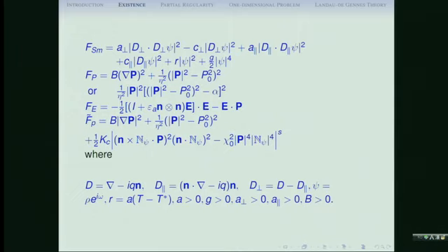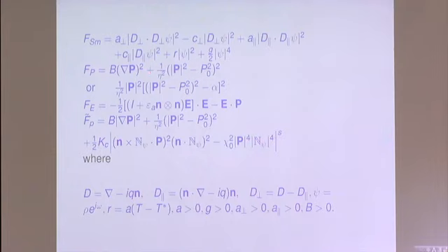When you consider antiferroelectric cases, you can put up to sixth order terms, and then if you want to, you can also put divergence P minus C0 squared, such terms. Oh, yeah. So there are many different terms. You can also have terms like divergence P dot curl P, as in the nematic director field, and you can also find those terms from Lagerwall's paper, 1982. You have the terms by using symmetry arguments. He found many different terms.